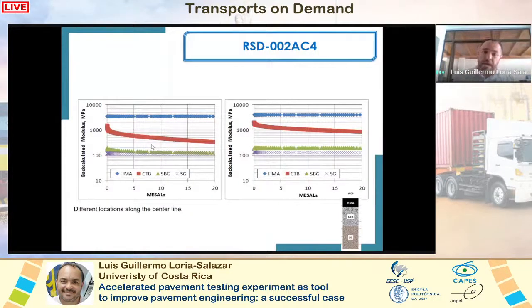This is a very important chart. I'm going to focus only on the one on the right-hand side. It's the same as what I just talked about. You can see in blue how the HMA moduli almost did not change through the whole experiment. And you can see this experiment reached 20 million repetitions. But the red one is the cement-treated base, and the moduli start decreasing with time. At the end of the experiment, you still have a very good strength in the cement-treated base, much higher than the sub-base. But you see that the damage of this pavement structure was taken by the cement-treated base.